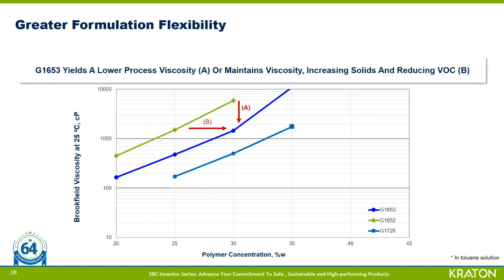But then we also have a second knob B, so we could maintain viscosity to increase the solids concentration. So in this case, we're taking G1652 from 25%, and when we swap out with G1653, we may be able to increase our solids up to 30% while still keeping similar viscosity. So this lowers the amount of solvent used and will result in less VOCs in the application coating. Here, G1726 is used only as a reference for illustrative purposes, since it also has low viscosity, but realizing the strength and flexibility is not necessarily the same as that of G1652 or G1653.